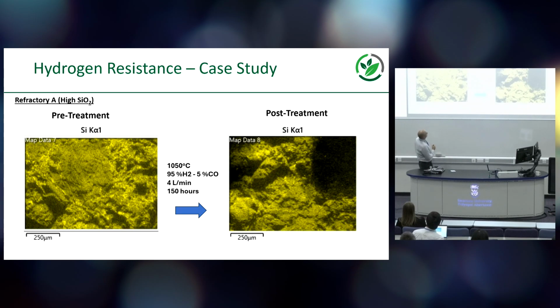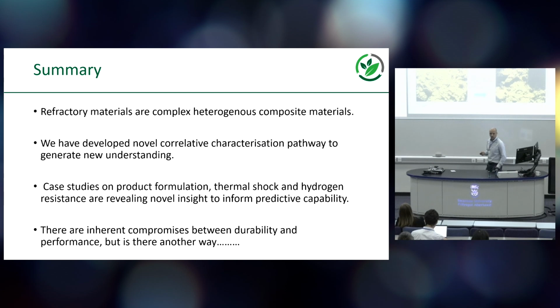We've also noticed, it doesn't come out very well on this screen actually, that the silica on the surface of the sample is significantly reducing, or the location of that is significantly changing before and after the hydrogen treatments that we're putting together. And so we hope to be able to present in future a direct correlation between these before and after microstructures so that we can understand more about that technique.